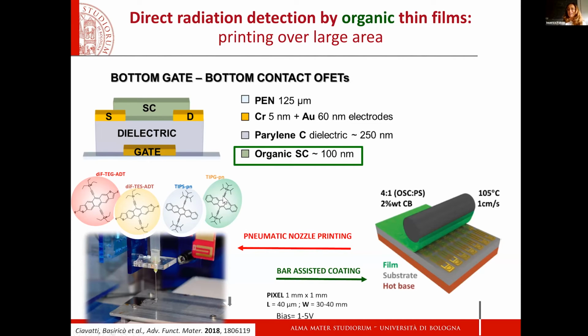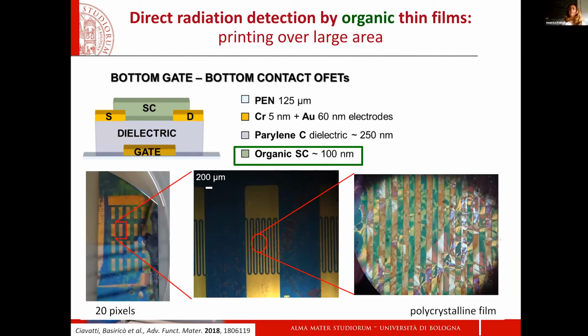Why is it interesting? Because you will see in the next graph that by simply changing the atomic number of one atom in the molecule, we can increase the absorption of high energy radiation of the material and therefore improve the performance. So that is what a typical 20 pixel matrix looks like, fabricated, as you can see, on a flexible PEN substrate. Each pixel in this case is a very simple interdigitated source drain structure with a bottom gate dielectric, and the film has a polycrystalline form.